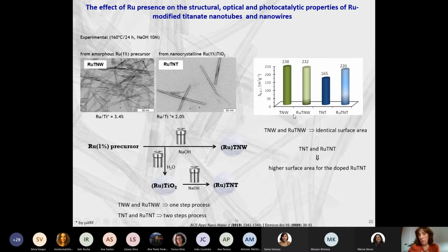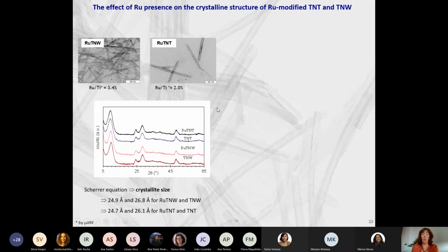Well, if we are interested in using these materials for photocatalysis, it's very important to know the surface area of these materials. This is the BET surface area, and as you can see, for nanowires we have almost no differences. It's not the same when we are talking about nanotubes. We have a difference between the ones prepared with ruthenium or without ruthenium. After that, we need to know where the ruthenium is. As I told you, we can have ruthenium in the interlayers or doping, replacing the Ti4+. And if we look at the XRD results, we can calculate the size of the crystallites, and we can see that in both cases we have a decrease in the particle size of these crystallites due to the incorporation of ruthenium.